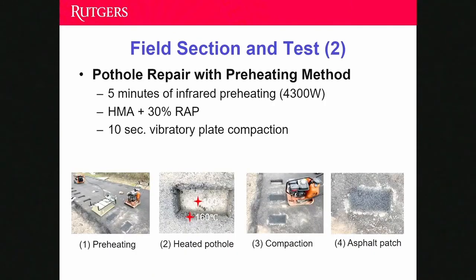And based on our previous study in this project, we have evaluated the heating performance, as I just mentioned. So based on those results, we applied 5 minutes of preheating here. We used a portable infrared heater, and its power was around 4,300 watts. And if we look at the second picture, after heating for 5 minutes, the temperature of the bottom of the asphalt patch would be around 100 degrees C, and the edges were up to 160, which means a good heating performance.